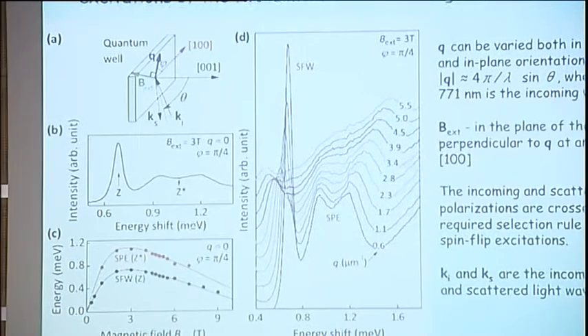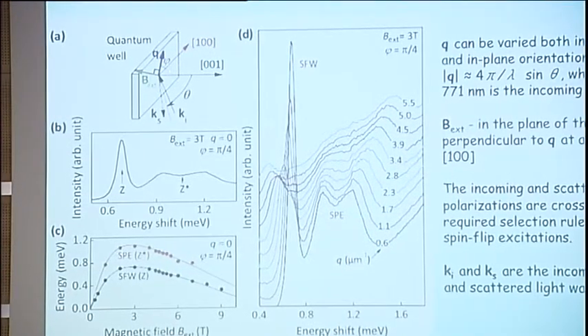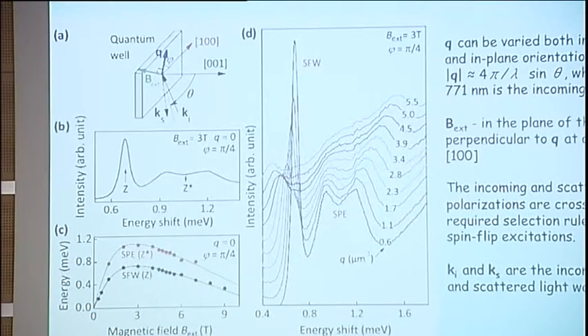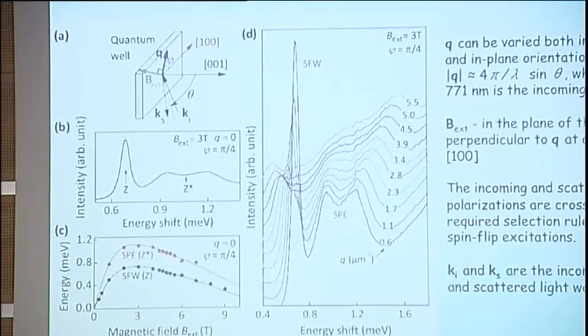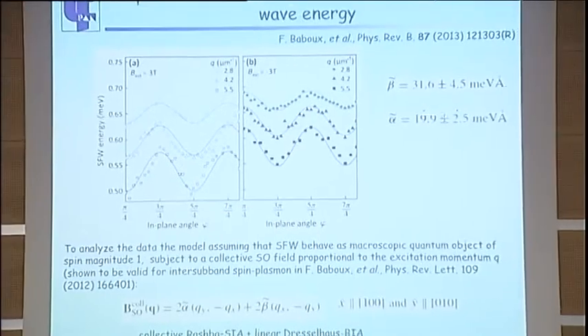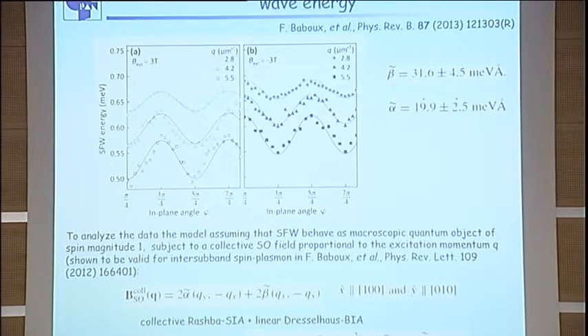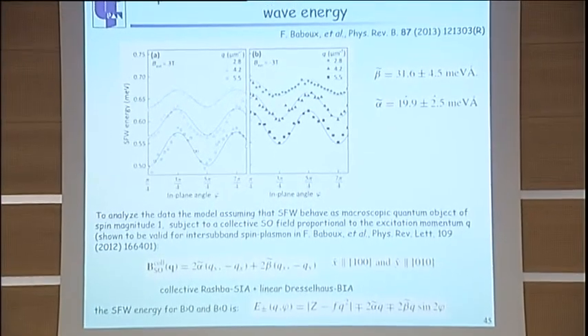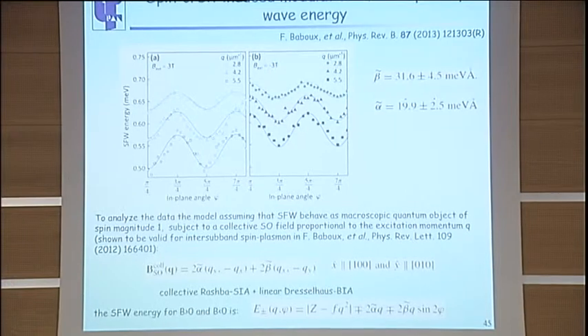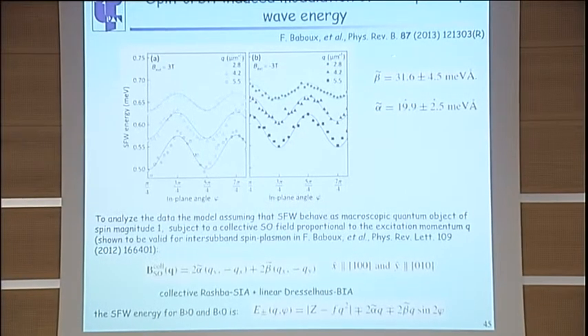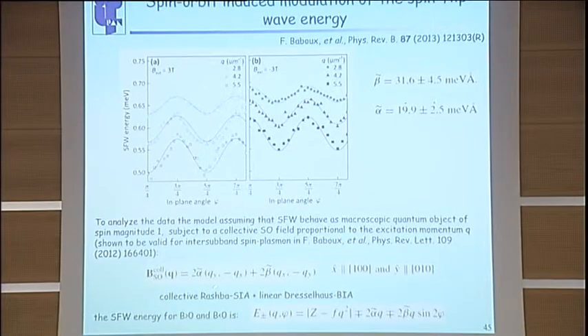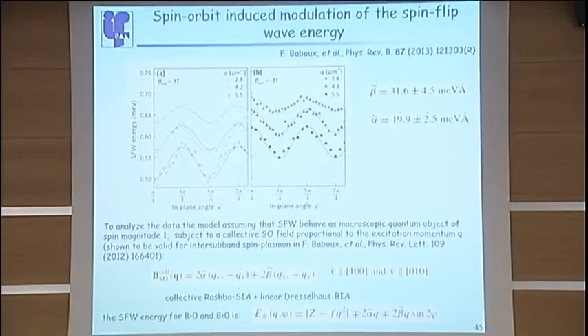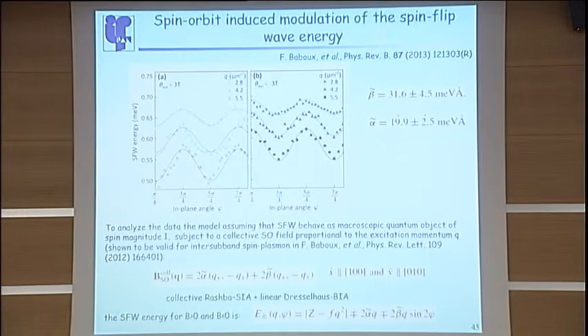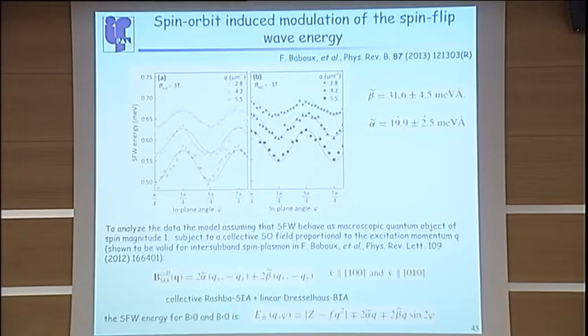So they have used, I don't have time to go into details, but they have performed the studies as a function of Q, for different data collected for different angles, and also they have shown that from the studies as a function of angle between the polarization of the light and crystallographic axis, they can determine the collective Rashba, so spin structure inversion asymmetry, and bulk inversion asymmetry, Dresselhaus linear terms.